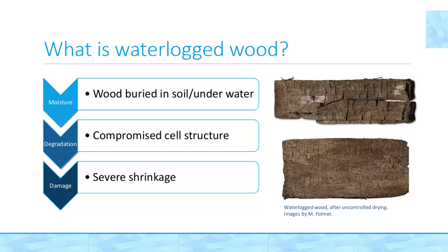Then, after hundreds and sometimes even thousands of years, when this wood is rediscovered, it may appear to be in perfect condition. But this is not the case. When excavated, the degraded wood cells are internally supported by the water, but as soon as this water starts to evaporate, the wood will start to shrink, crack, and warp significantly. This results in significant damage, in particular cross-grain checking, as you can see on the images on the right here. Naturally, we want to prevent this, which is why a conservation treatment is needed.